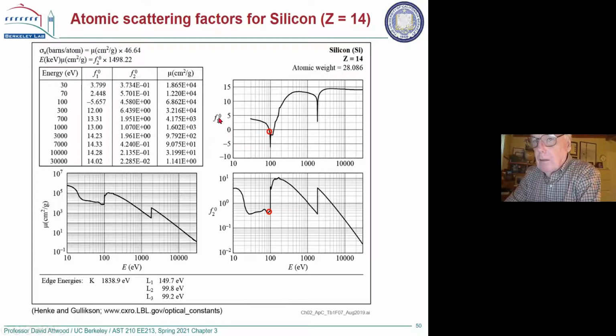because the real part, delta, is going to be about 0, and beta, it turns out, is also quite small. You're just below the absorption edge. So as you're increasing photon energy, going up, up, up, there's not much absorption until you get to the L edge, and you can kick out an n equals 2 electron, and now you've got a lot of absorption. So just stay below that, and remember that these atomic scattering factors, the units are electrons.